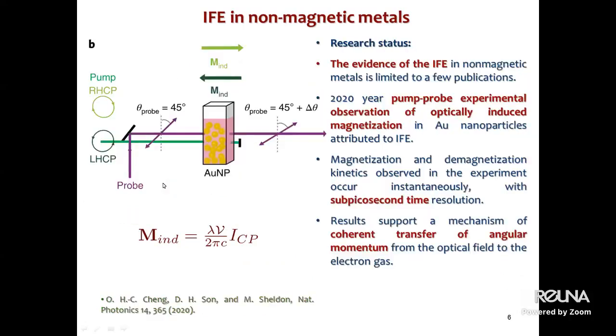Now, what about current research status? So far, experimental evidence for the inverse Faraday effect in non-magnetic metals remains limited, with only a small number of reported studies. A recent pump-probe experiment, reported 5 years ago, to some extent recent, reported optically induced magnetization in gold nanoparticles and also attributed to the inverse Faraday effect. The observed magnetization and demagnetization dynamics are ultra-fast, occurring on sub-picosecond timescales. These results support a picture of coherent angular momentum transfer from circularly polarized light to the conduction electron gas.